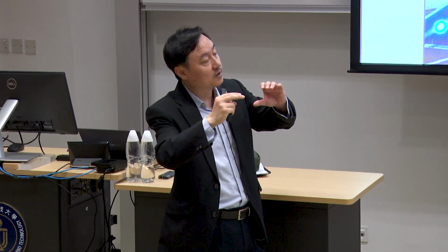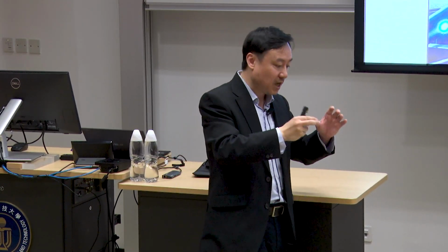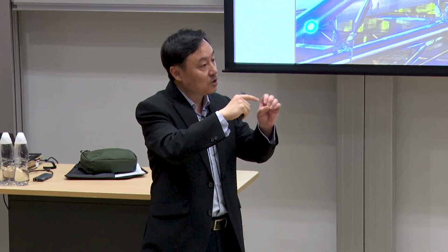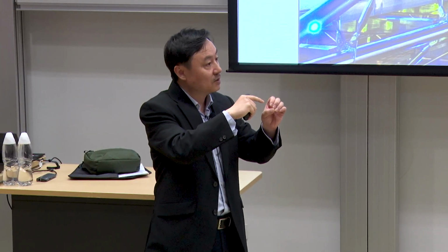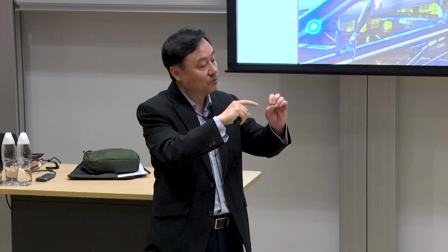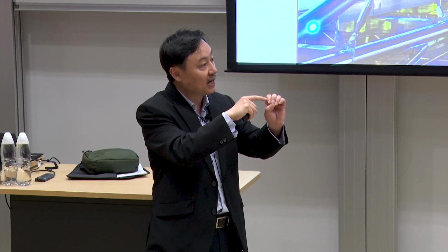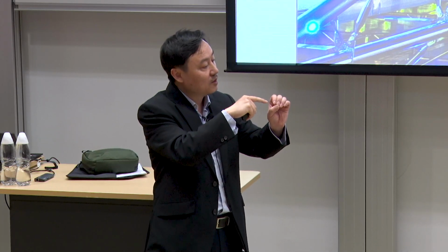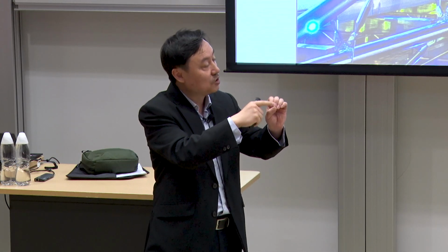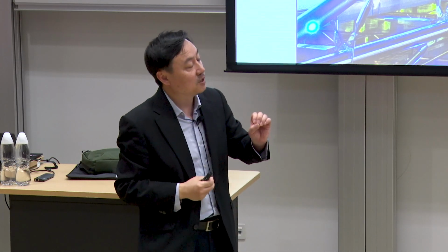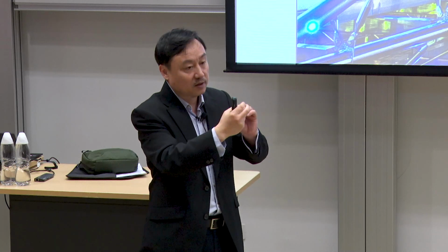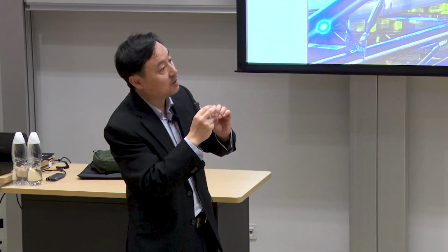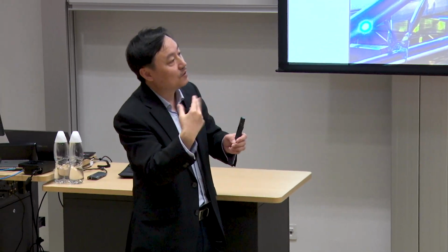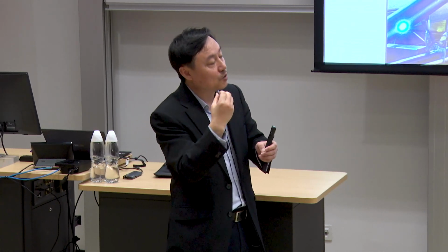So the water molecules, remember most of the upconversion I mentioned involves energy migration. So migration happens within the particles. It means if the particles emit light, not only the core, but it can actually transfer to the shell. The shell layer also has the emitters. If the water contacts this emitter, the water has a strong vibration frequency, so it quenches luminescence.